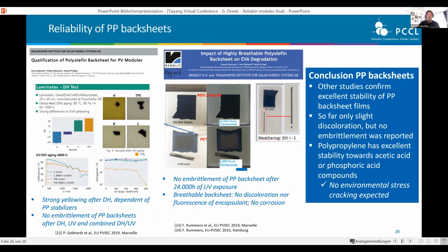Renolit, François Rummens, hello François, I saw you are online. They presented also results on their polypropylene backsheets, and I think the conclusion from all these studies is the same. So far, we see an excellent stability of PP backsheet films, especially towards UV. So Renolit did like 24,000 hours of UV exposure and didn't see any discoloration of the encapsulant or embrittlement or corrosion. Fraunhofer just saw yellowing, but in dependence of which kind of stabilizers were used. And that's the only thing that was reported.